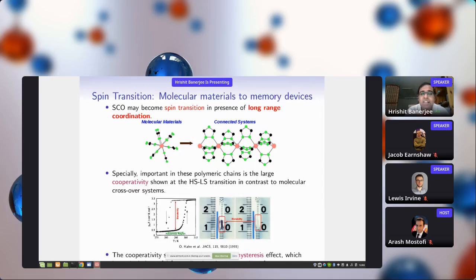materials such as these. And experimentally, this is from an experimental paper, it is seen that these coordination polymers basically show hysteresis in their magnetic properties with temperature. And this hysteresis is also manifested as a bistability at a certain temperature, as you can see from the experimental figure here, where they show that at the same temperature you can have 2 states at 2 different colors. The colors indicate the spin state changes as well, which is also a very interesting thing, which I'll come to later. And the cooperativity is basically manifested as a hysteresis effect.